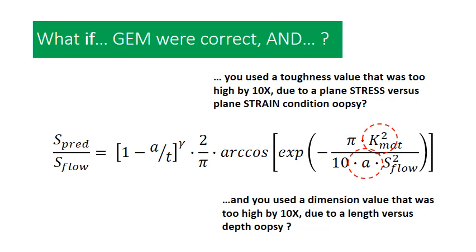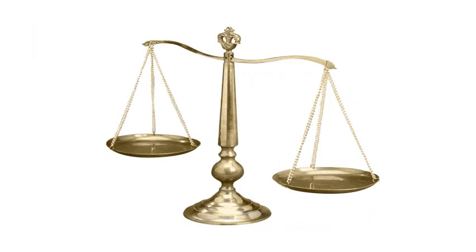And you would expect that having a number that was off by 10 times would jump out at you and tell you that there was something wrong with the model. However, in this particular case, we have a number on top of a fraction that's 10 times too big, and we've got a number on the bottom of a fraction that's 10 times too big. And those two errors completely or mostly balance each other out.